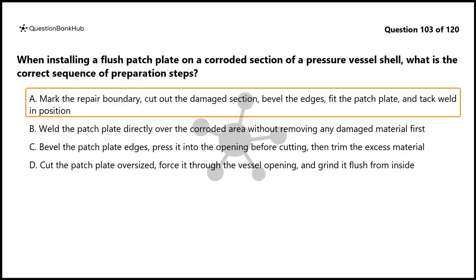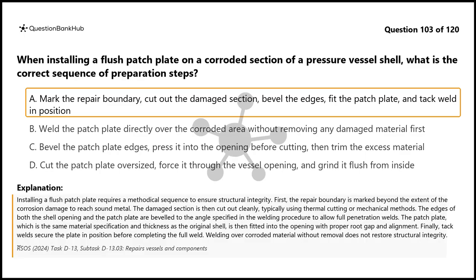The correct answer is A. Installing a flush patch plate requires a methodical sequence to ensure structural integrity. First, the repair boundary is marked beyond the extent of the corrosion damage to reach sound metal. The damaged section is then cut out cleanly, typically using thermal cutting or mechanical methods. The edges of both the shell opening and the patch plate are beveled to the angle specified in the welding procedure to allow full penetration welds. The patch plate, which is the same material specification and thickness as the original shell, is then fitted into the opening with proper root gap and alignment. Finally, tack welds secure the plate in position before completing the full weld.